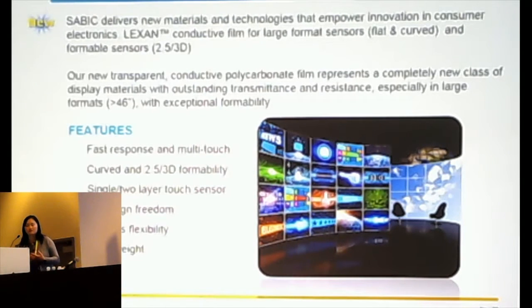Its electrical conductivity, the resistivity, is lower than the current ITO solution by almost 5-fold. That will provide a very quick response. And by the way, because it's a polymeric solution, it's basically a functional polycarbonate film, it's flexible. Imagine when you use your touch screen, it's almost always glass. The reason being that if it's not flat, then the current conductive material, which is ITO, will break. It will cause bad pixels, and it will actually malfunction.